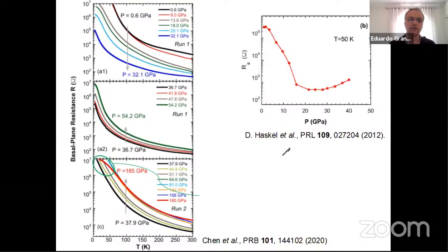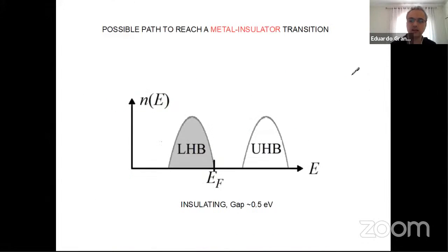So first we tried, not only us, but many groups tried to induce the metal-insulator transition in the iridates by external pressure. But it turns out the resistivity of this material actually decreases with pressure, as expected, because the bands become broader, but then it doesn't go to a metallic phase. It saturates in a still very highly insulating phase, and even after the pressure increases, the phase doesn't go metal. So in these iridates, at least up to more than 100 GPa, it's not possible to induce a quantum phase transition by the application of external pressure.